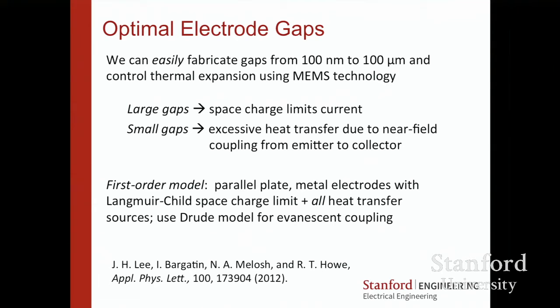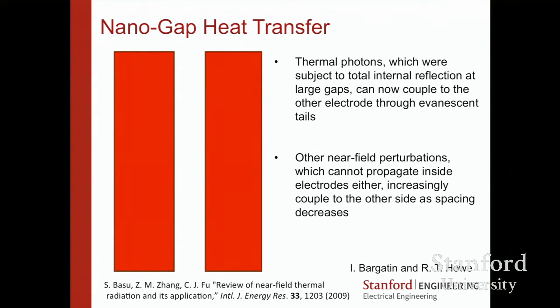Langmuir-Child law. If you get really small, that looked kind of attractive, but lately people have been looking at heat transfer in tiny, tiny gaps, and it turns out you get coupling between surfaces through the vacuum. It's kind of evanescent heat transfer, and so there's an Applied Physics Letter that looked at this, and there's a lot of things that happen when you get close. You can have photons that reflect, but then couple to the other side if you're in a close enough gap, and you get heat across. You can have near field perturbations, all kinds of different things that we modeled and borrowed models from the community to see what the optimum would be.